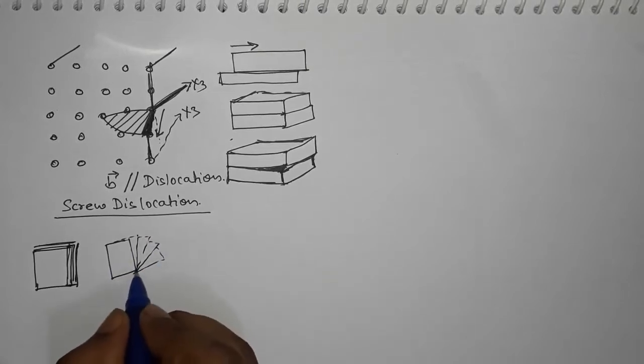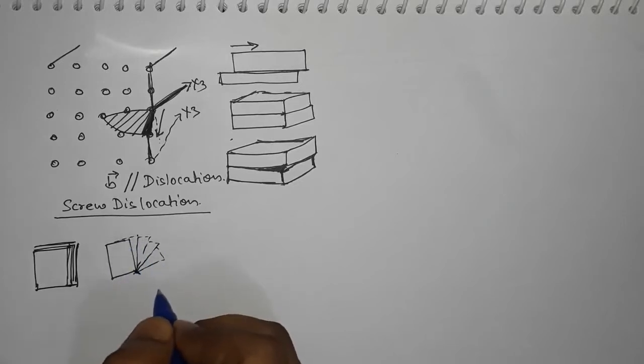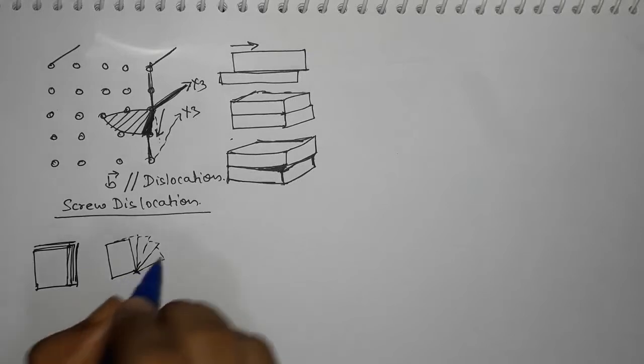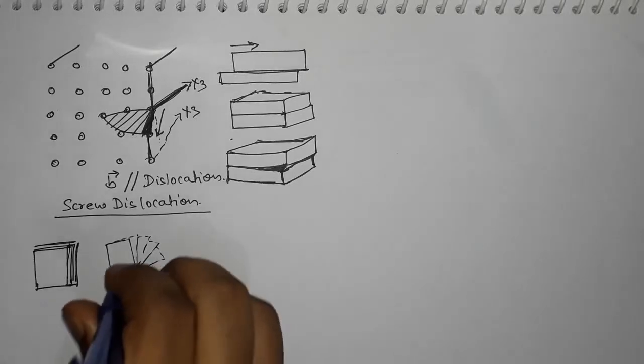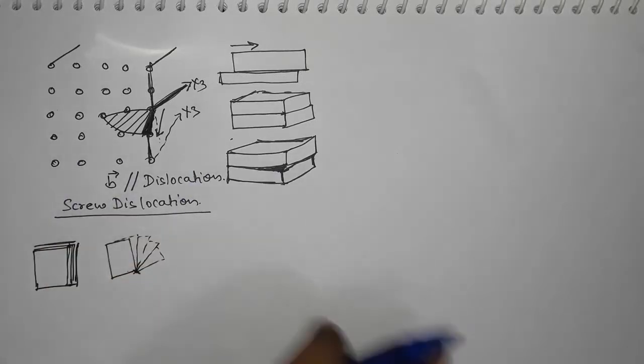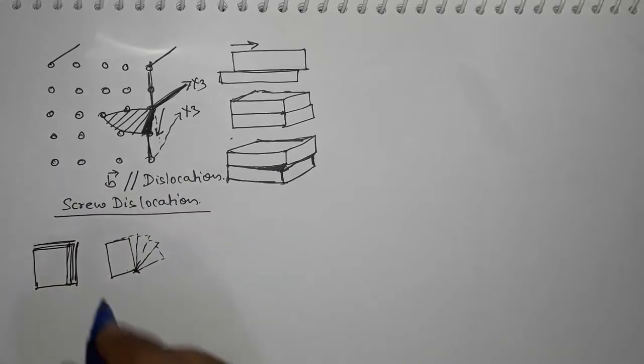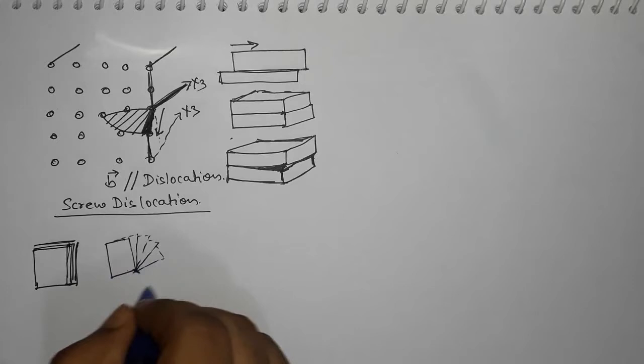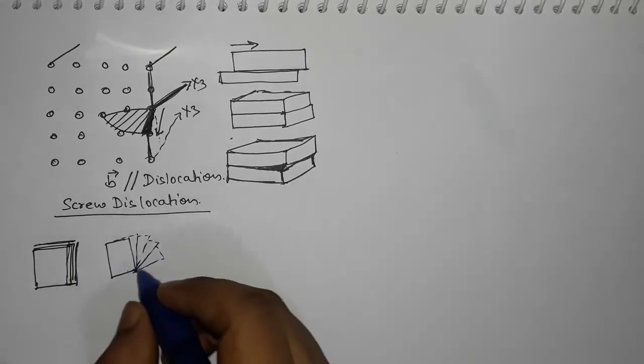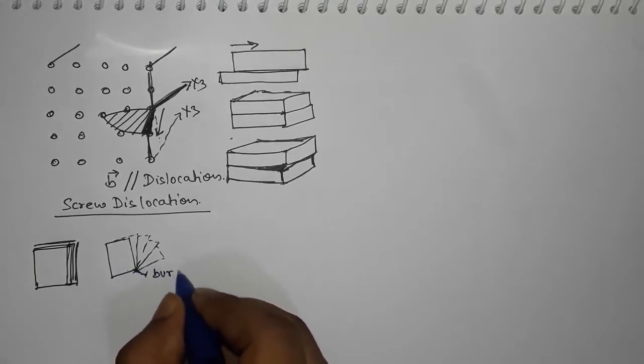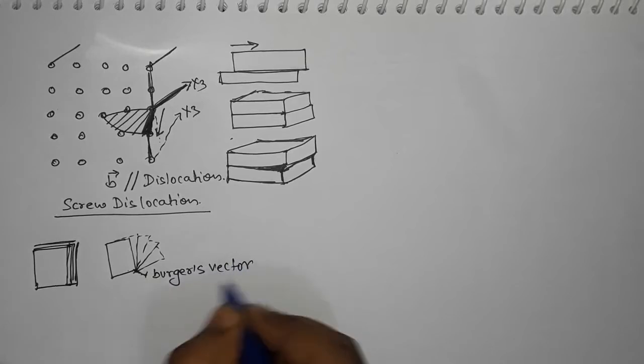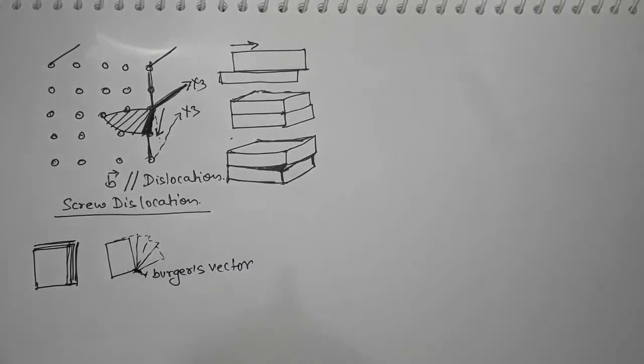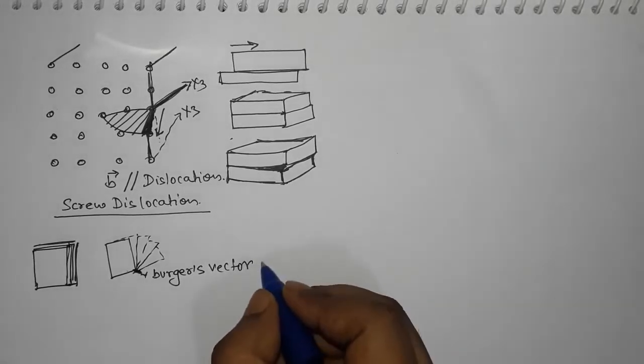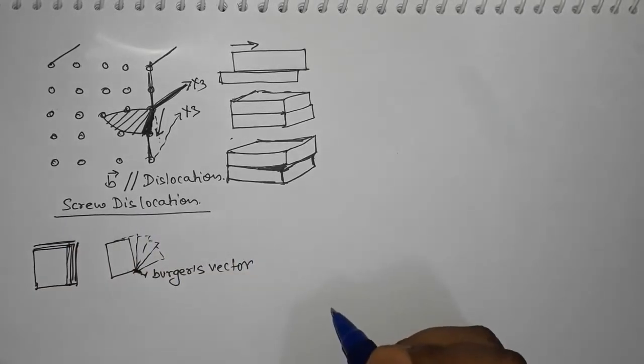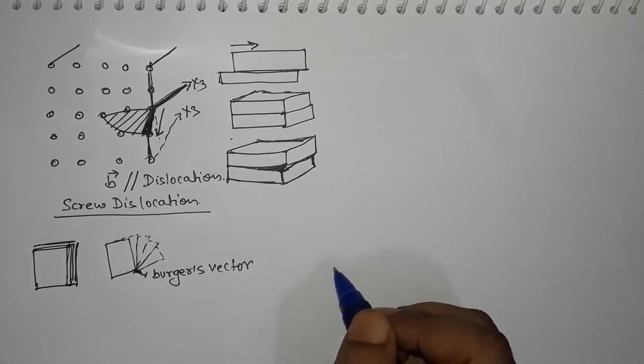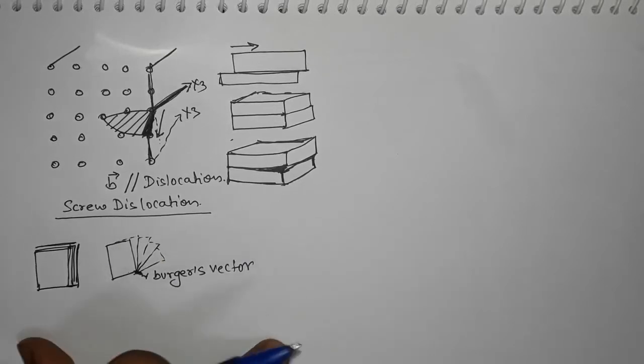So the dislocation line and the Burgers vector are actually moving in the plane of the paper, perpendicular to this paper, and it is going downward, so it's like a helix which will go down in the plane of paper. So that is the direction of the Burgers vector. And this is the line of dislocation, which is parallel to it, and therefore it is a screw dislocation. So these are the two types of dislocations which we have in the material.